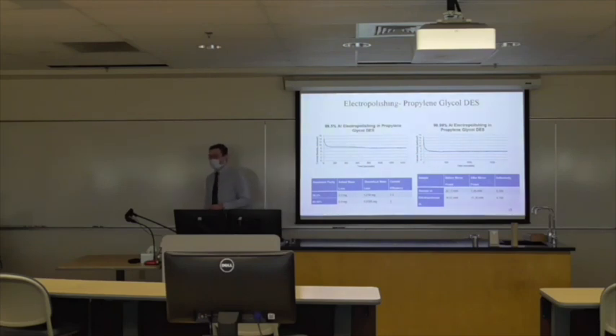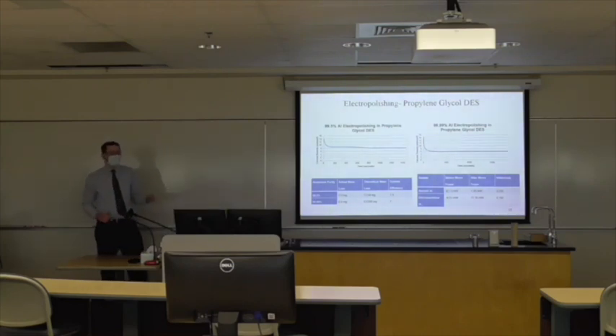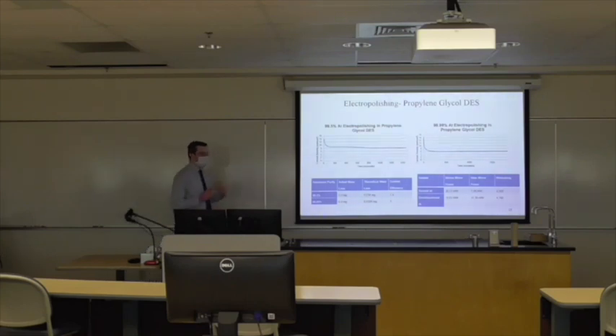The interesting part about this is we then were able to use this electropolished aluminum to see how well it works for our further processes. So, what are those further processes? Well, the actual production of the aluminum oxide templates is where we had to go next. Rather than with 0.3 molar oxalic acid, we used 0.75 molar oxalic acid, the premise being that it would improve the time that it takes to anodize. So instead of taking 160 hours, we're able to accomplish it with just an hour of anodization at 50 volts.